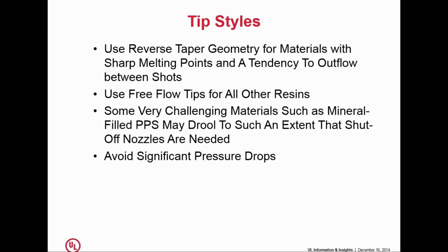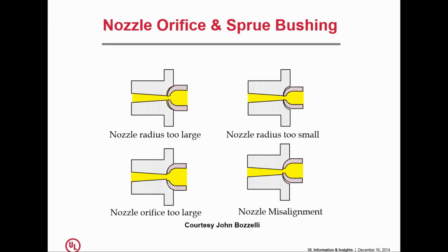And then once you've got the thing on there, make sure to pay attention to the picky details. Radius too large, radius too small, what's that going to result in? Either plastic collecting here and the sprue sticking, or leakage and the sprue sticking, or if the nozzle orifice is larger than the sprue bushing, the sprue sticking, or if the nozzle is not properly aligned, there's an undercut here and the sprue sticking. You know, these are all the things that we just simply try to fix by just shoving a piece of cardboard in there and hoping the problem will go away.